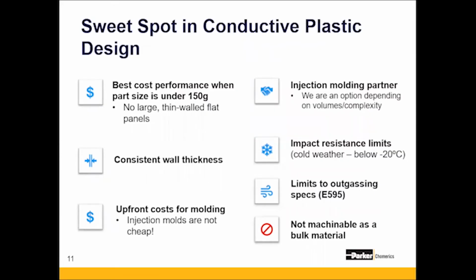Okay, so we get right into the sweet spot in conductive plastic design. There's a couple things to consider. Conductive plastics work very well when they're designed in the sweet spot, the geometry, the molding parameters, but keep in mind parts should have a 1.5 to 3 millimeter wall thickness. Ideally, they have to be consistent walls. You don't want different thickness walls. Obviously, that's just a regular plastic molding thing anyway, and you also don't want the part to be too much larger than 150 grams. So the larger the part, the lower the cost performance. It's one of the sweet spots.